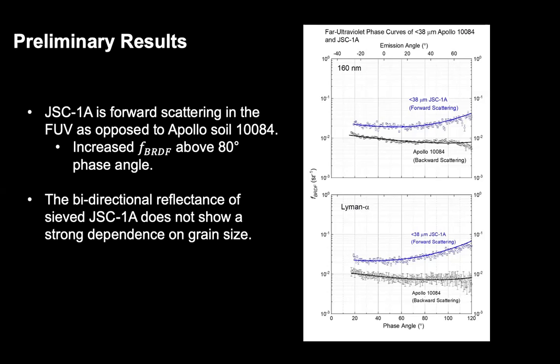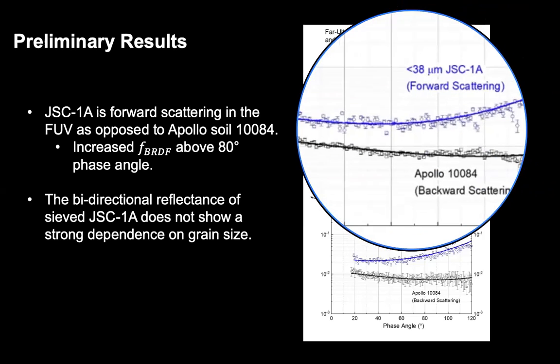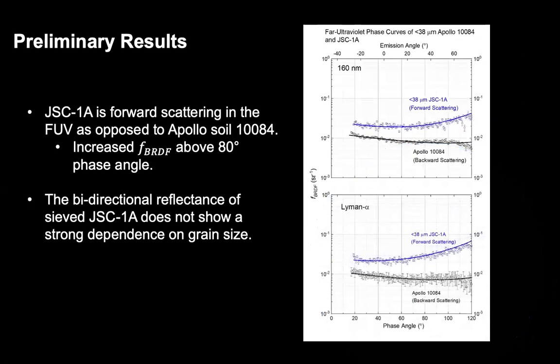Plus, the JSC1A overall appears to be a lot brighter than what the Apollo 10084 is. And I'll show a plot of that here in a few moments. Again, we are moving away from really doing a lot of investigation of grain size because preliminarily we found that the sieved JSC1A does not really show a strong dependence on the grain size. In other words, the reflectance properties really did not vary that much between one grain size and another in these very preliminary measurements.